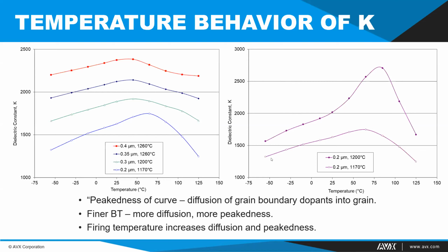Certainly, one thing we have discovered over the years is that the quality of the barium titanate that you use can have a big impact on this kind of behavior. Materials that have very fine or very high crystallinity, in other words, no disordered material that tends to be on the outside of the grain, tend to give us the best results in this way.